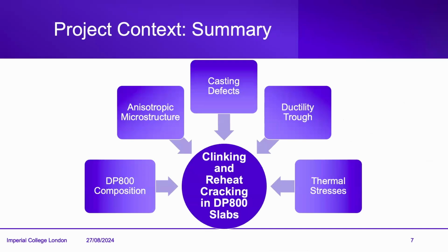So to summarize the context, you've got a peritectic composition from DP800 steel, anisotropic microstructure due to the nature of continuous casting, which can also introduce casting defects into the material. And then you've got a ductility trough at certain temperature ranges. All of these are interacting in a slab, which is subject to thermal stresses upon cool down or reheating.